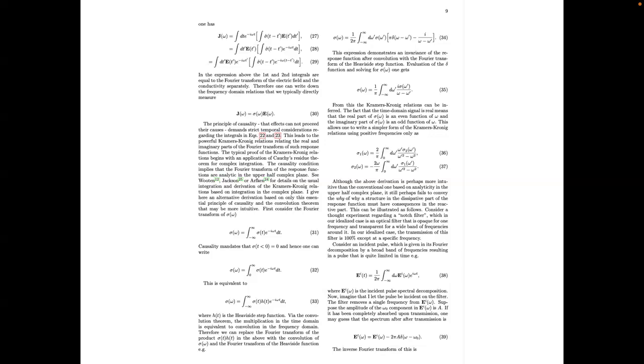I'll show you data like that. So we know sigma 1 and sigma 2 over a particular frequency range. We know both of them, and we can use our knowledge of the Kramers-Kronig relations to tell us things about parts of the spectrum that we haven't actually measured. That sounds perhaps a little like magic, but in fact this is what we do all of the time when we're measuring a quantity like the superfluid density. In a superconductor, the conductivity at zero frequency is a delta function, which has a particular area, and an important physical quantity is the integrated weight in that delta function.